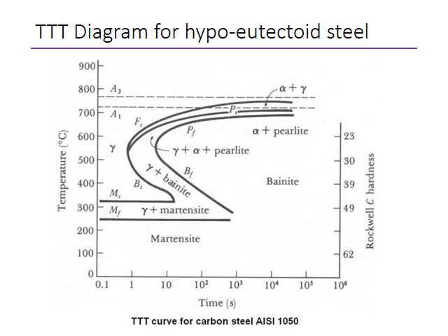So we can say that above this temperature, you will create pearlite. Below this temperature, you will create bainite. In the middle of these references, you can further elaborate and start to say, well, this should be the line. That's fine. So above this, you have pearlite plus primary ferrite. And below this, you have bainite and no primary phase anymore.